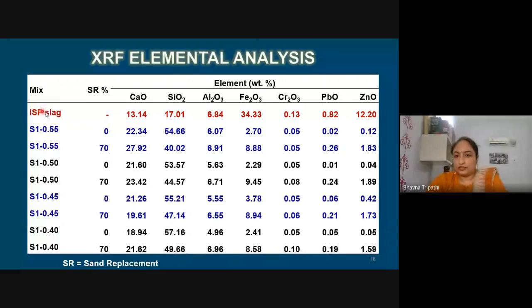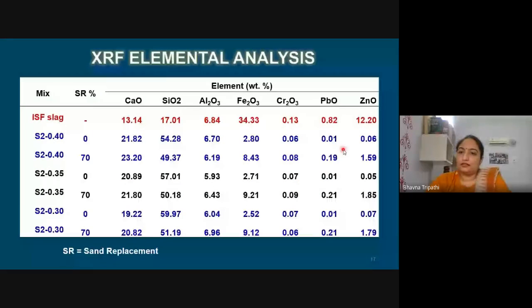In ISF slag, as you can see, there is a percentage of lead and zinc. However, when we see the concrete mixes XRF, we don't find an appreciable amount of lead and zinc, which was expected, and this was promising also. The other water cement ratio mixes also showed a similar kind of XRF oxide analysis. The percentage of lead and zinc was very marginal, which is also attributed to the presence of lead and zinc in cement. Cement also has very trace amounts of all metals.